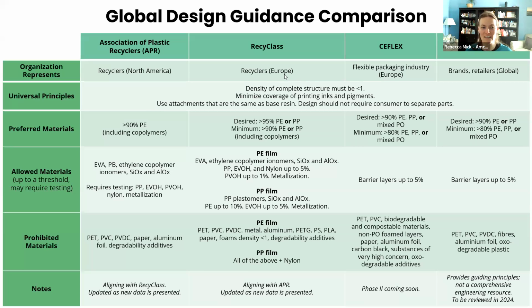All right, when we get into the allowable materials, it gets a little bit more varied, but you'll see there's still a lot of commonality here as well. So again, for the PE stream for APR, we're allowing EVA, which is commonly used. It's a copolymer commonly used in things like retail bags. Polybutene is a common material for easy opening features, right? So when you're peeling it apart and you can do it with your hands without scissors, that's often PB. Ionomers, another common material used, also a copolymer of polyethylene, no problem. SiOx and AlOx and metallization, all of those are inorganic barrier coatings that are used in very small amounts, and usually fine, with the exception that the metallization needs to sort correctly.